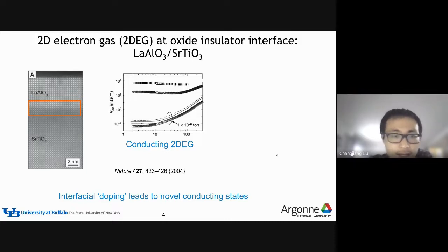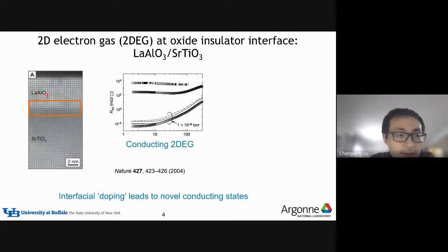Showing on this slide is an example. People found that when you put an oxide insulator, for example, here it is lanthanum aluminum oxide, so let me bring my pointer. So lanthanum aluminum oxide is an oxide insulator. When you grow this material on another oxide insulator, which is strontium titanium oxide, both of these materials are insulators. However, when you grow this material on top of the other one, it turns out that the interface becomes very metallic and very conductive, and the mobility can be very high.